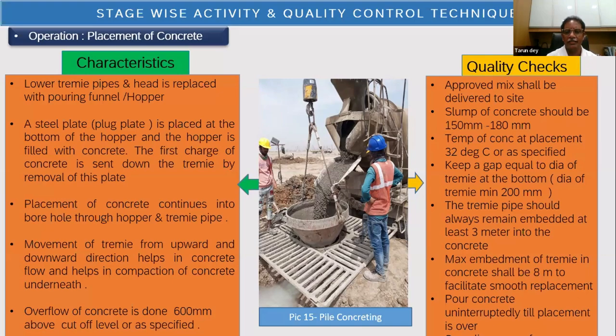Now there will be a plug at the bottom of the hopper. First you fill the hopper, then pull the plug so that the concrete rushes down the tremie, goes down and replaces the latent scum at the bottom and takes the position. So the first charge replaces the bottom scum, if any is left after flushing. The good concrete takes the place and the contaminated concrete comes to the top. That's why I call it the replacement process. Subsequently, you keep on pouring the concrete, and terminate and cut the tremie, removing the tremie as the concrete shaft develops with respect to time and the pouring of additional concrete.